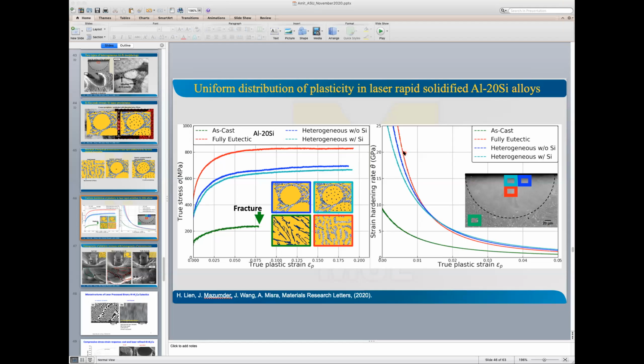Yeah, this is a great talk. Thank you very much for it. So my question was that, typically it appears that with the laser surface treatment, this would be a replacement for, say, applying a film on the surface. So instead of coating something with a material that is stronger, you would just modify the surface with this laser treatment to make it structurally more sound. So my question was, have you considered just pulsing a lamellar or layered non-hierarchical film with laser to see if it reintegrates into a hierarchical structure? Just to see if something that is already decomposed can again reintegrate into something hierarchical.